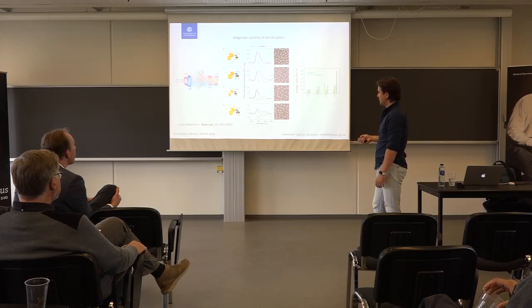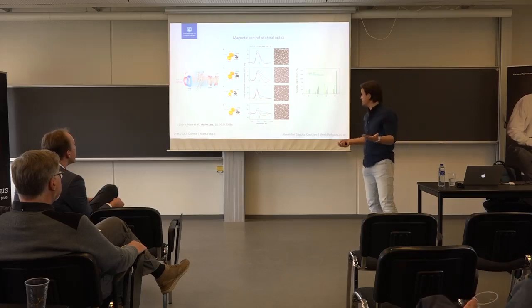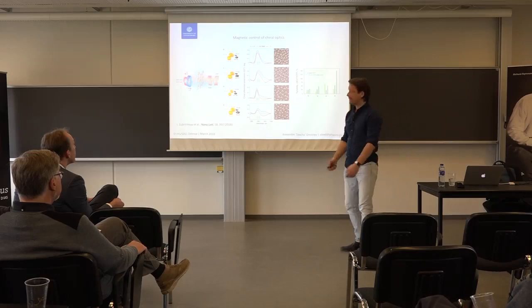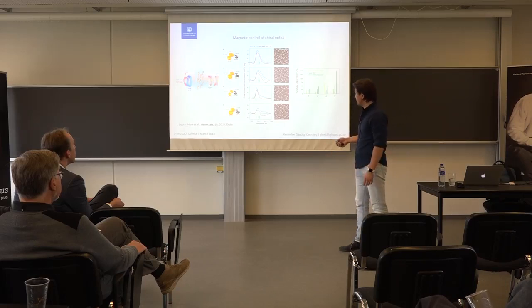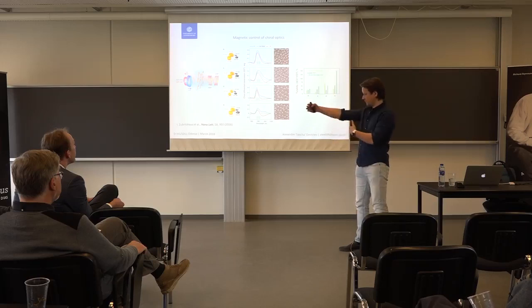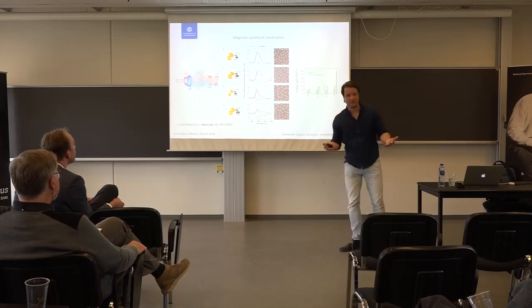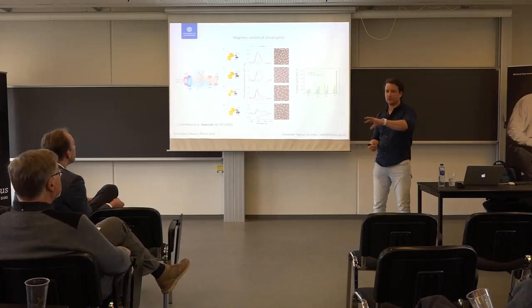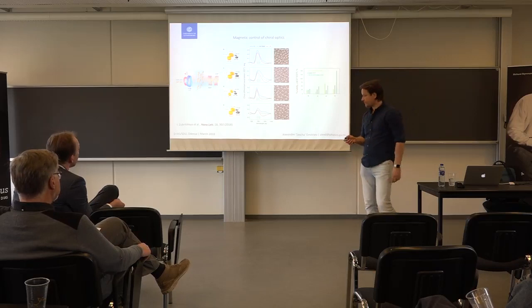You can change the gaps, and at the end you can map the tunability, how much you can tune that system, and it turns out that in certain configurations you can tune it up to more than 100%. So if your original response is somewhere here, you can actually change that by more than 100% in terms of how much circularly polarized light comes out.